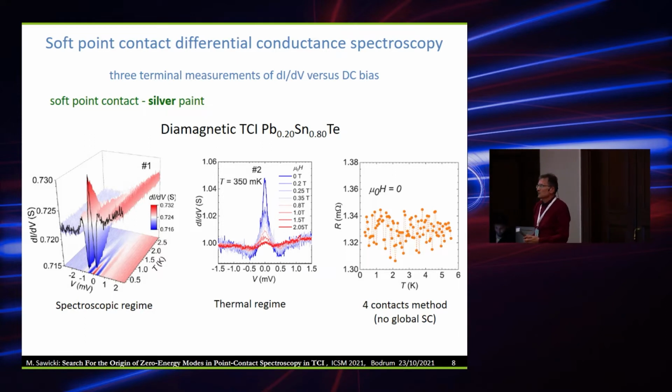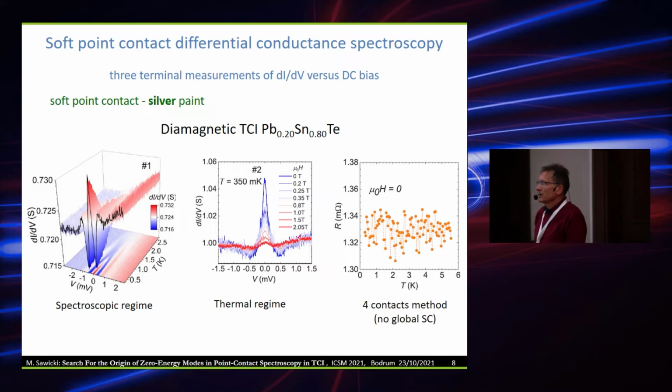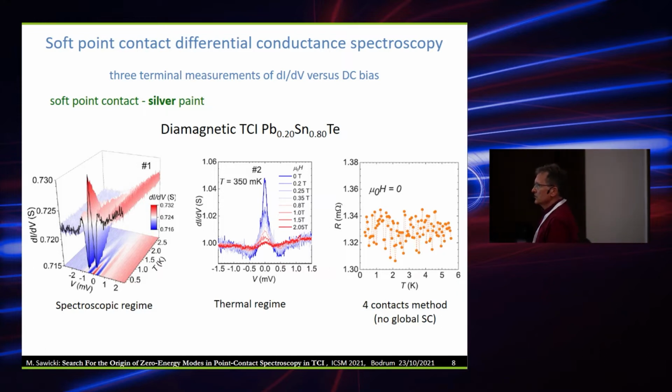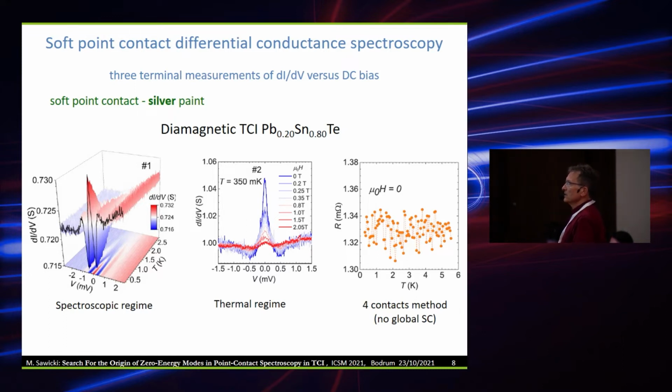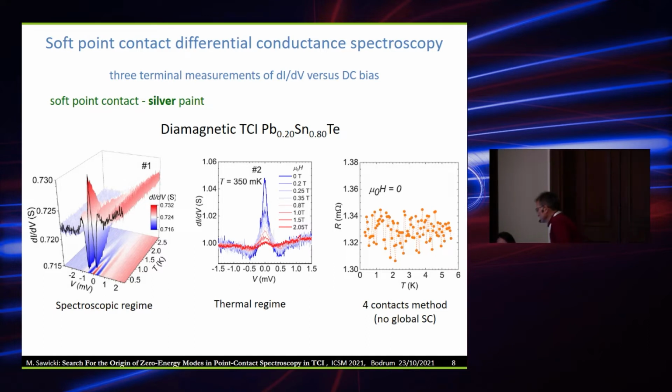these modes are actually very robust. That was another surprise for us. For example, they can survive with the temperature to more than 2 Kelvin. Concerning the magnetic field, they can survive up to 2 Tesla. And this is the first experimental result, I mean this one.